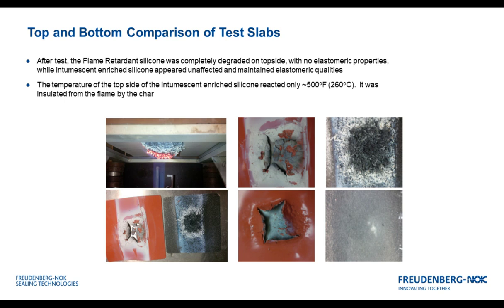So shown in the middle is a conventional UL94 so-called flame retardant material that had the same exposure to the flame, and it had burned completely through. The photo on the right shows the side that intumesced. This is the side that was directly exposed to the flame, and the lower picture is the top of that 2 millimeter test sheet. Clearly, there was a substantial protection there.